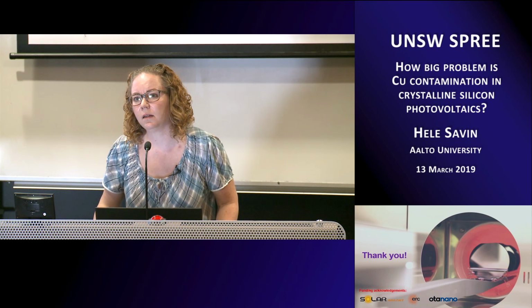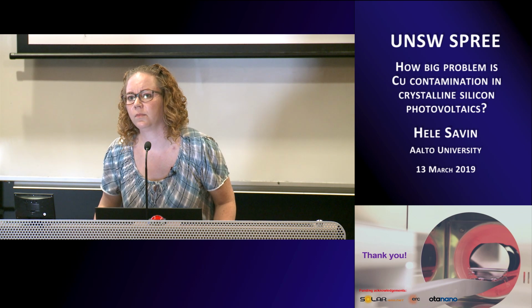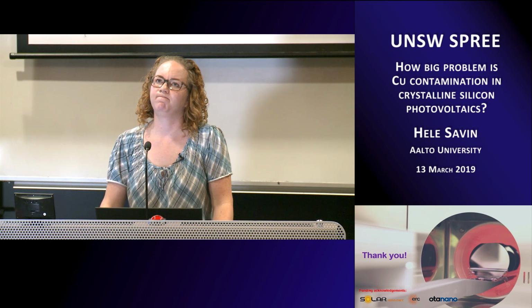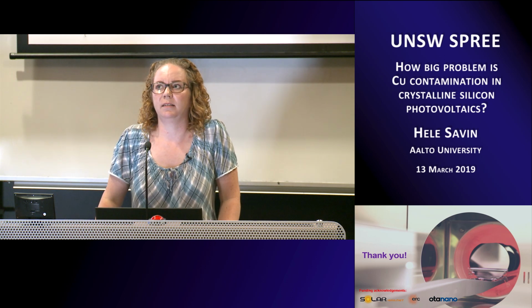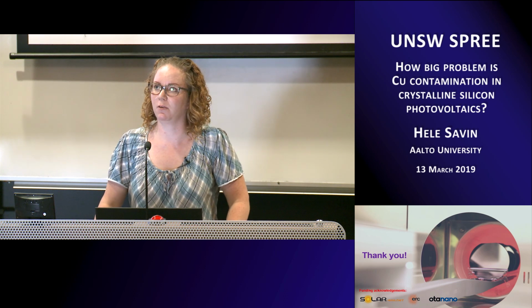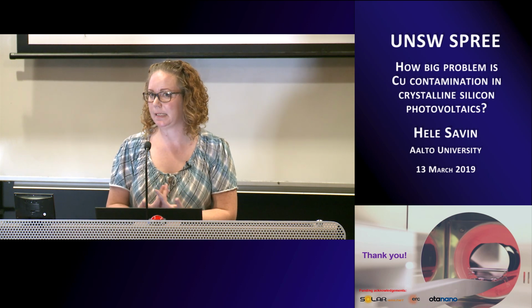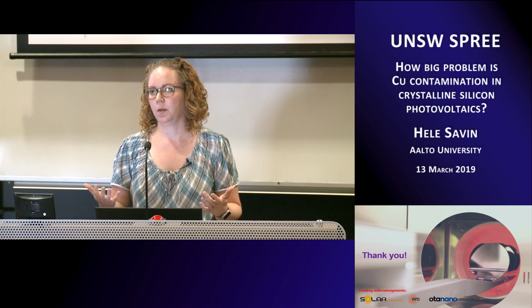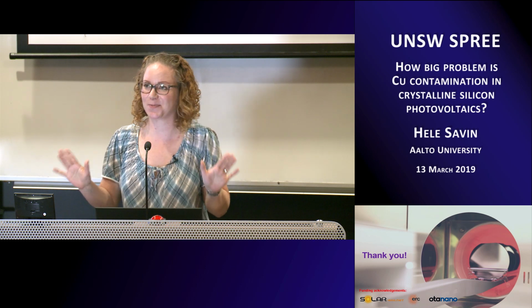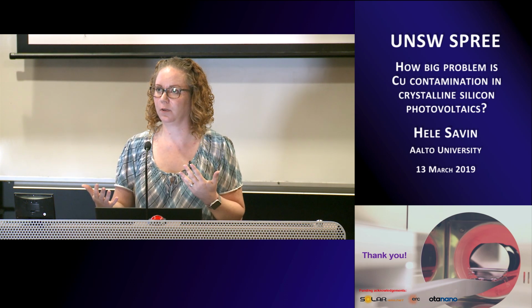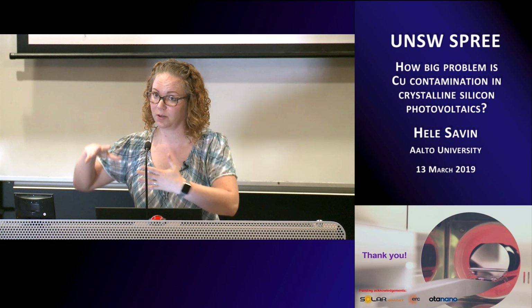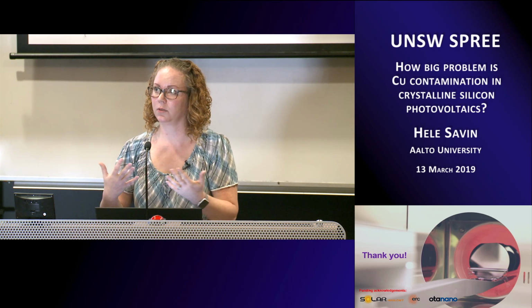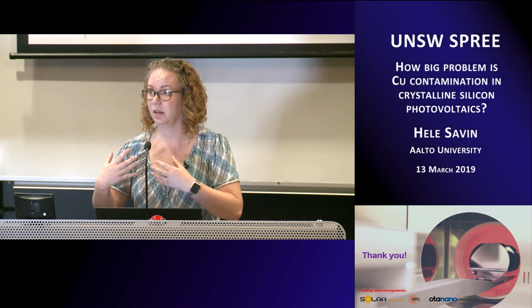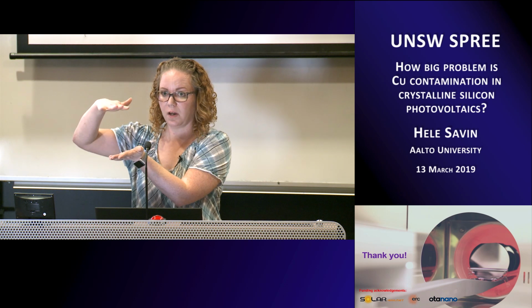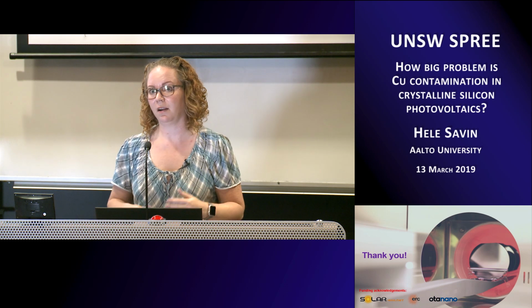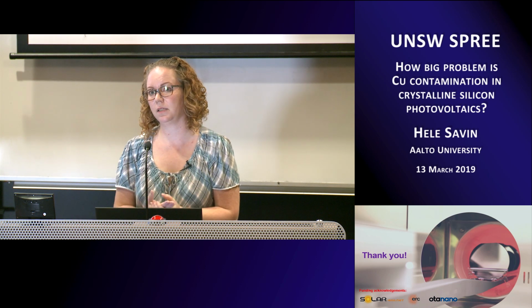And what about the presence of oxygen and boron? How is the presence of oxygen and boron helping the copper LID, helping it to diffuse faster? Yeah, this is my speculation about the role of boron. We know that the copper solubility depends on the boron concentration. I don't have proof, this is pure speculation, but if you have higher boron concentration in your wafer, you have higher copper concentration, because your solubility is higher. So boron is not directly involved in the process. If you have a specific amount of copper at your surface, the more boron you have, the more copper you will have, because it depends on this solubility.